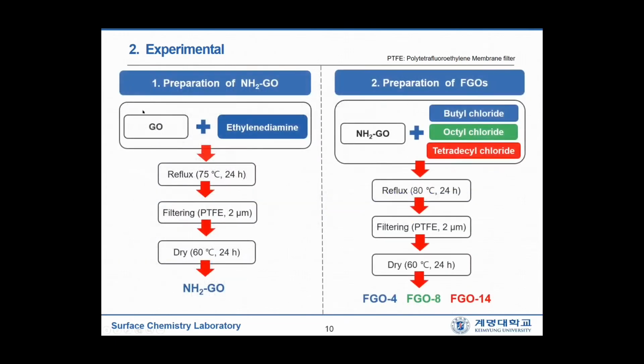The first step of functionalization of graphene oxide is the preparation of aminized graphene oxide. Graphene oxide and ethylene diamine are mixed together and refluxed at 75 degrees for 24 hours. Then the product was filtered by PTFE filter with 2 microns of pore size. Finally, the product was dried at 60 degrees for 24 hours to get aminized graphene oxide.